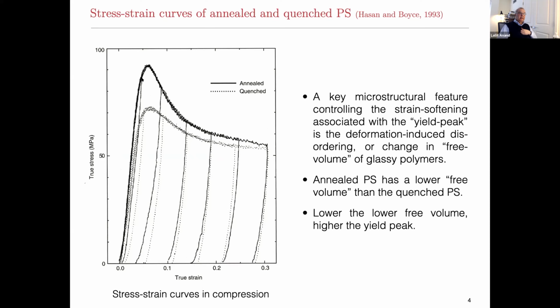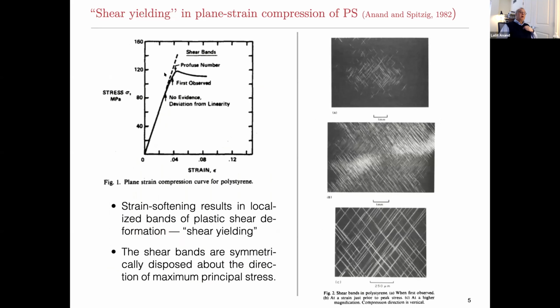The other thing to note is that this is an unloading curve. There's also plasticity prior to the peak. People call this the yield peak, but in fact there is plasticity prior to the yield peak in the material. Because of the softening at the yield peak, you actually get strain localization. You get shear bands. In fact, plasticity in these materials is due to the formation and multiplication of the shear bands. This is in polystyrene.